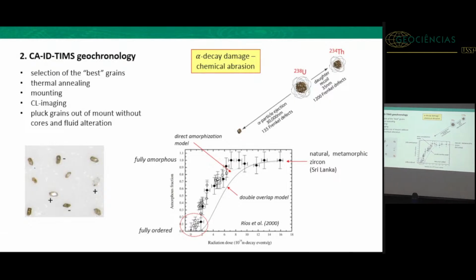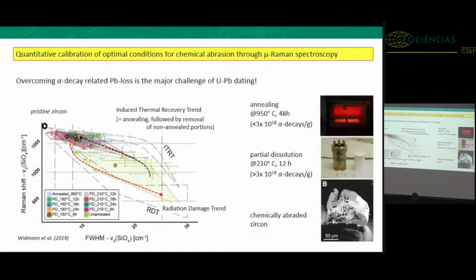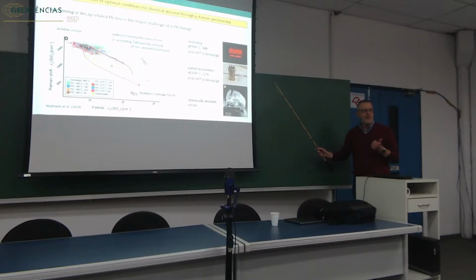This is the process we are using with every single grain. First, we anneal it at 950 degrees for 2 days, and we repair the parts of the grain which have some damage, and then we dissolve away the parts of the grain which had more damage. So we end up with a zircon which hopefully represents only material at the first percolation point, which will hopefully give us an answer which represents the growth age of the material.